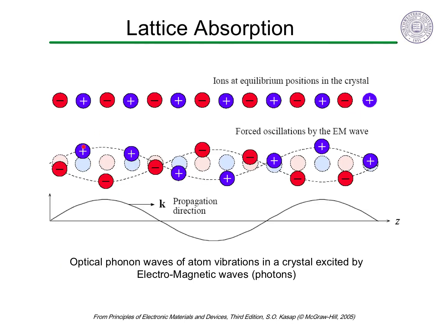The lattice vibrations or phonons themselves can also absorb and emit photons. Because ions in a solid are also charged particles, they easily couple to electromagnetic radiation. Because the phonon energies are in the milli-electron volt range, the photons that couple are in the far infrared.